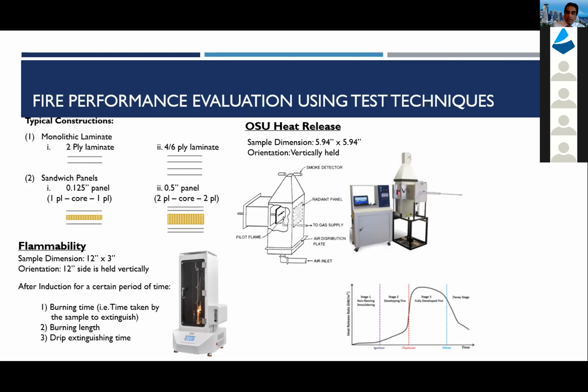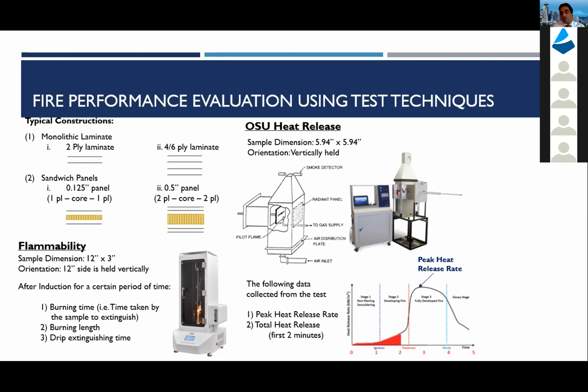And the graph at the bottom shows a typical trend of the OSU curve. It plots the heat generated from the material as it burns through different phases, from the non-flaming phase to the fully developed fire phase. From this curve, the information we collect is peak heat release rate and total heat release in the first 2 minutes of the test. And the test is usually carried out for 5 minutes.